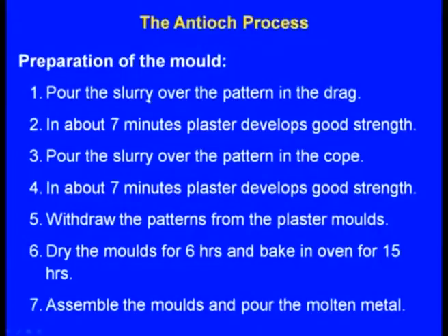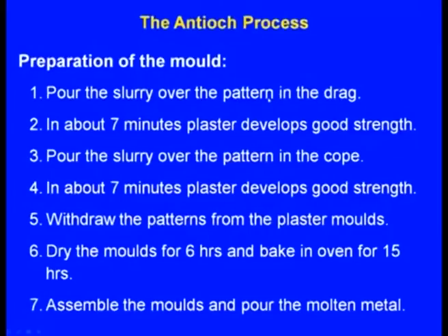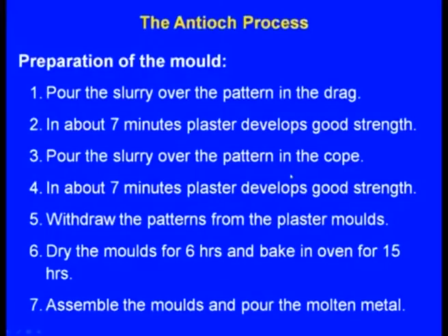Now preparation of the mold. After we prepare the slurry, pour the slurry over the pattern in the drag. In about 7 minutes, plaster develops and gains good strength. Pour the slurry over the pattern in the cope also in the same way. In about 7 minutes, plaster develops and gets good strength.